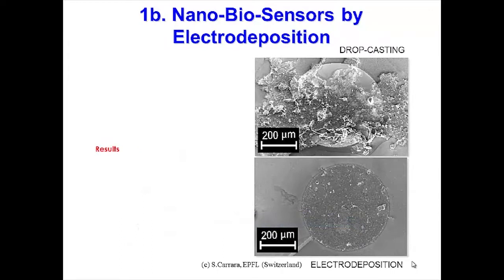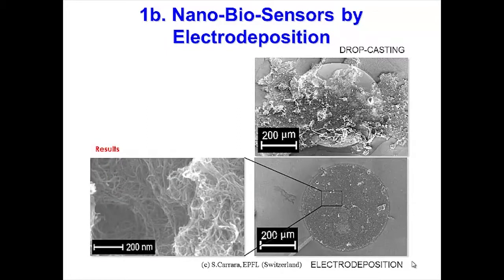This is just a comparison with what we obtain with drop casting. As you can see, there is not such high precision on these round electrodes, while with electrodeposition we obtain a much better coverage of only the required region. Of course, this borderline deposition can result in shortcuts, so it's kind of dangerous for our technology. Now, if we analyze the obtained forest, we see a result similar to what we obtained before in the case of drop casting. However, don't forget we still have the polymer in this case covering our carbon nanotubes.